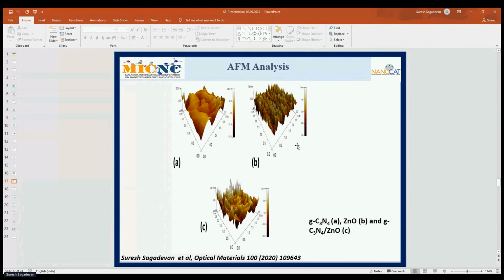Maybe the C is a topographical image of the composite, a well-arranged, homogeneous pattern in which the rods are immobilized with the graphitic carbon nitride layer, in good agreement with this TEM image. So all the physical and chemical characterization confirmed the successful formation of these three samples: graphitic carbon nitride, zinc oxide,